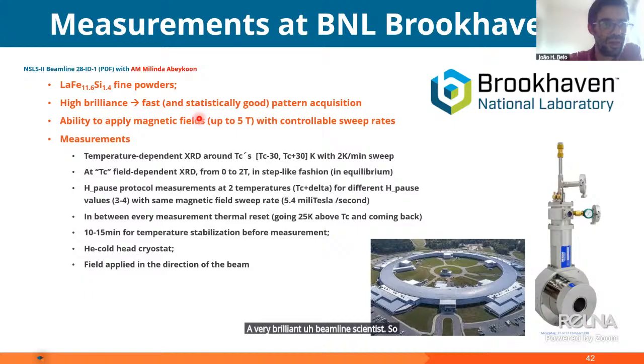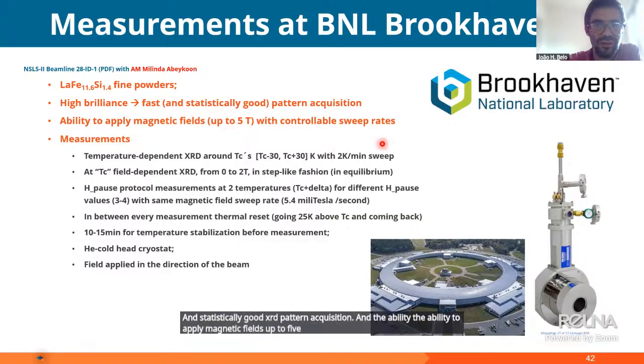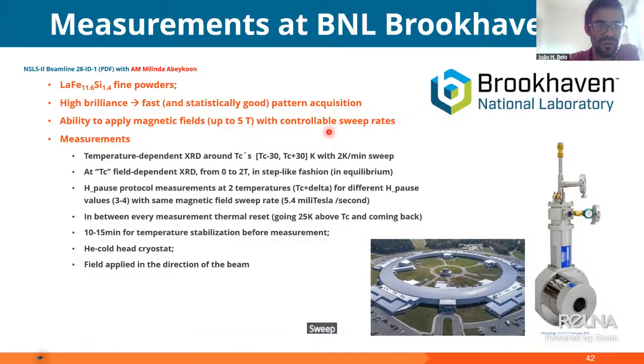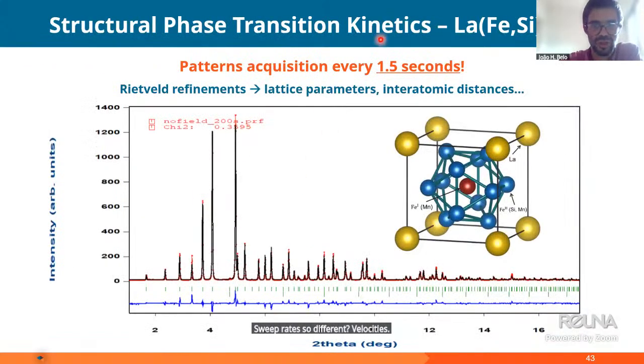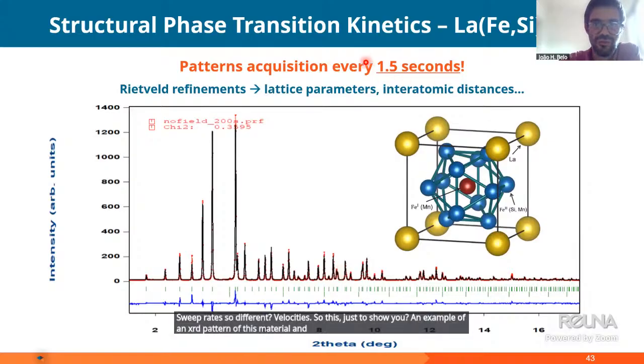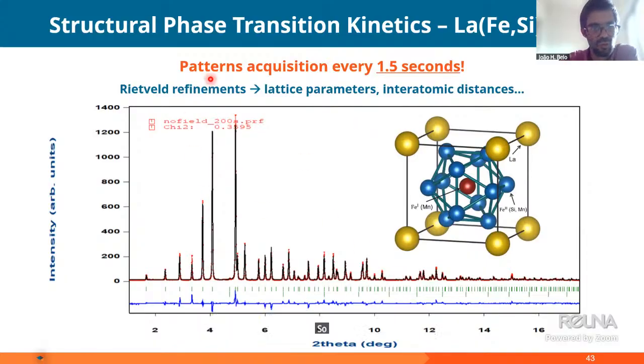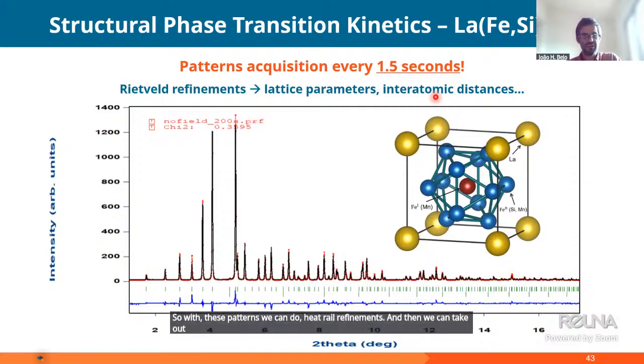We chose this synchrotron because of the high brilliance that enables fast and statistically good XRD pattern acquisition, and the ability to apply magnetic fields up to 5 Tesla with different sweep rates, so different velocities. This is just to show you an example of an XRD pattern of this material, achieved with a 1.5 second acquisition. With these patterns, we can do Rietveld refinements, and then we can extract the lattice parameter, the interatomic distances, and so on.